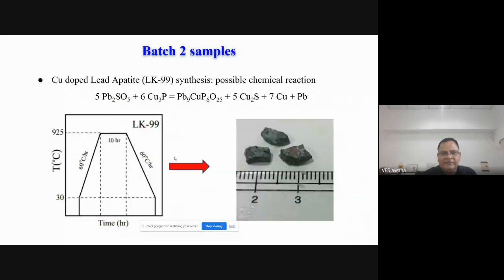Then from the same one we tried the LK99, and the pieces which came out are shown here. Another interesting thing which the Koreans did not tell is how Pb2SO5 and Cu3P lead to LK99. LK99 is Pb9CuP6O25 in fact, but if you mix them in a 1:1 ratio, which they wrote in their paper and they have a patent also in Korea, this does not lead to Pb9CuP6O25.